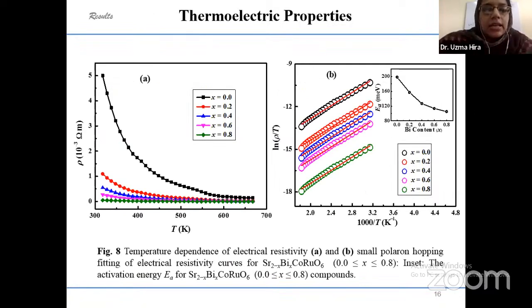And this is the electrical resistivity data for this series of materials, as a function of temperature. The curve represents a semiconducting type of material, because the electrical resistivity decreases with increasing temperature. And with increasing doping content from 0.2 to 0.8, the electrical resistivity decreases further. It means that bismuth is producing more carrier concentration in our system.